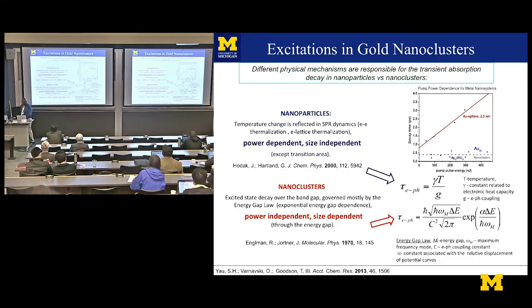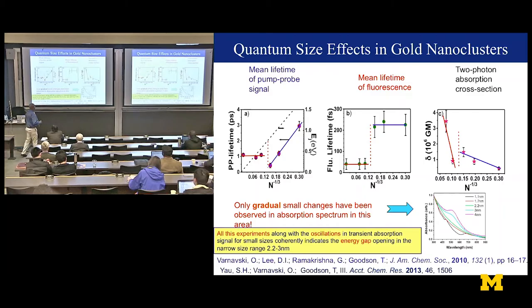What to do then? Well, interestingly, we tried to model these kinds of things. All right, so you said, well, your pump probe shows that as you make these particles and clusters smaller, there's some kind of cutoff between the behavior. This is the transient lifetime, okay? This is the fluorescence lifetime, and this is two-photon cross-section, and you could do the same thing with absorption. And it seems like a gradual small change is observed in the absorption. But all these experiments, along with the oscillations that I just talked to you about, suggest that there's something happening at about 2.2 nanometers. You're making this particle smaller and smaller till you get to about 2.2 nanometers, and it appears that the behavior changes.